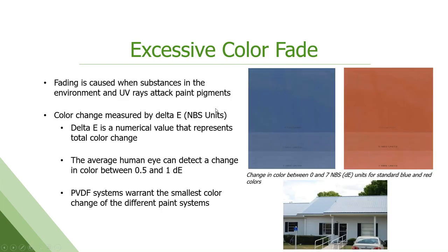Color fade, pretty self-explanatory. I think we're all really familiar with this, right? It fades. We measure it by what's called delta E, which is a color unit measurement, a numerical value that represents total color change. The human eye can detect this between 0.5 and 1 unit. The PVDF systems typically have the tightest color fade that's allowed, usually 5 units or less. So 5 units of color fade or less over anywhere from a 30 to 40 year time period, which is not a lot of color fade.